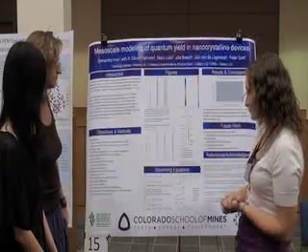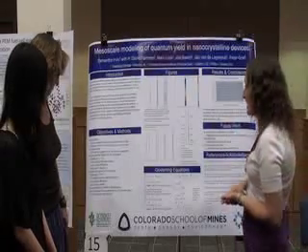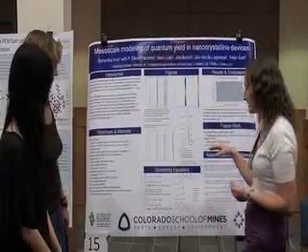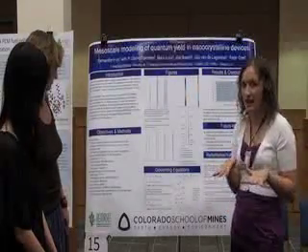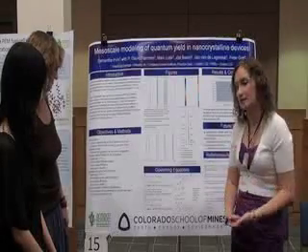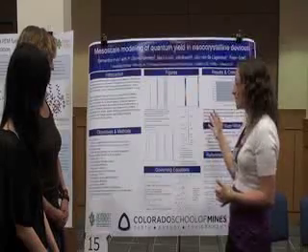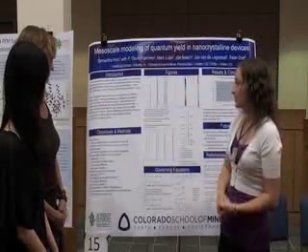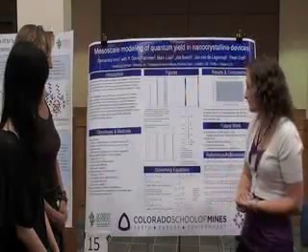with both of them. And what we did was that we put the nanocrystalline silicon quantum dots in our intrinsic region. It was an amorphous silicon intrinsic region, and we packed them at about 50%, and we kept that constant for this. And what I did was we had different modules set up with my model using COMSOL, and we ran the optical models in order to find what sort of scattering and absorption we get for different light.